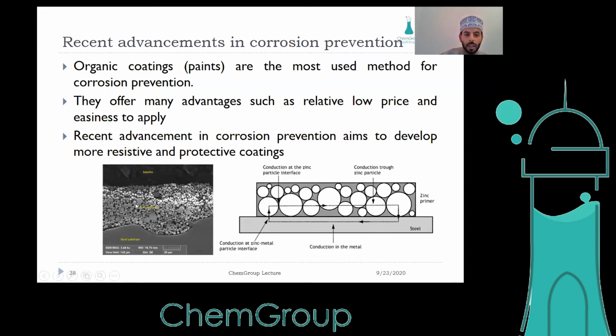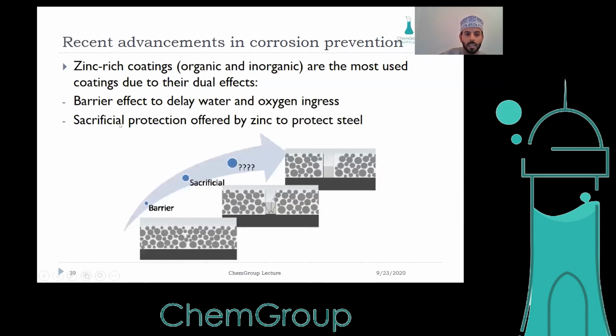And this is one of the most used paints nowadays, especially in marine structures. And why is that? Because it offers sacrificial protection by zinc to protect the steel. So if there is a scratch in the paint, the zinc will react as an anode, and it dissolves or corrodes and protects the steel substrate. But the problem is that when the zinc is disconnected from each other or from the steel substrate, it cannot offer any protection to the steel substrate.